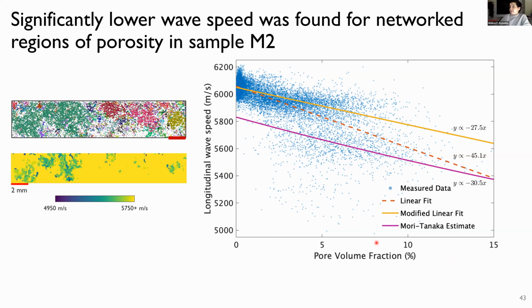But what we noticed was that if we were to threshold the wave speed by those values where we knew it was regions where there was highly interconnected porosity, then we see that the slope of the line, once you eliminate this lower data, is actually a lot closer to that Mori-Tanaka estimate in the response.